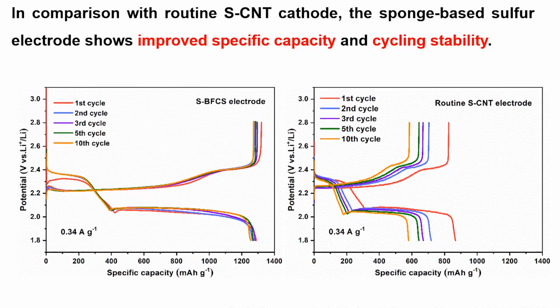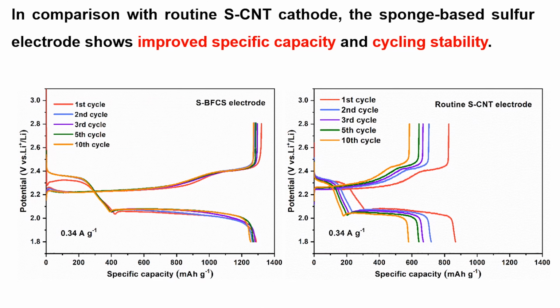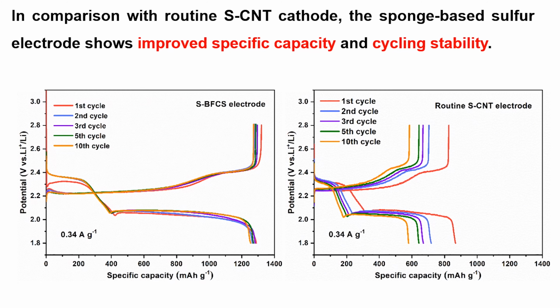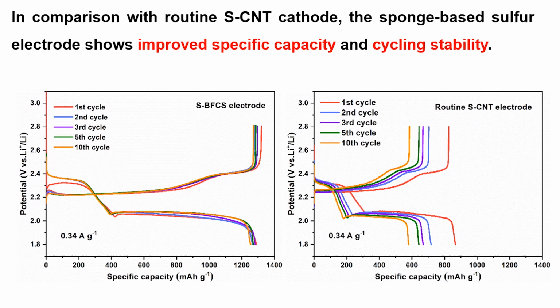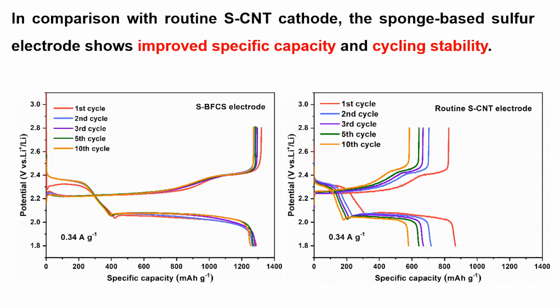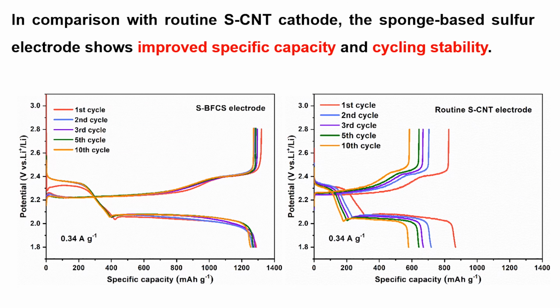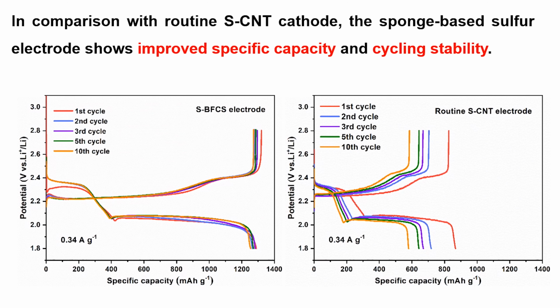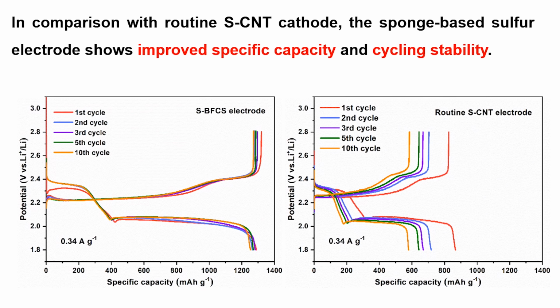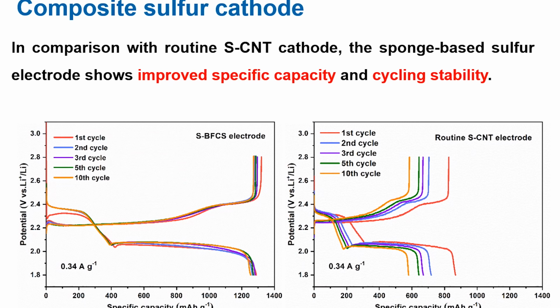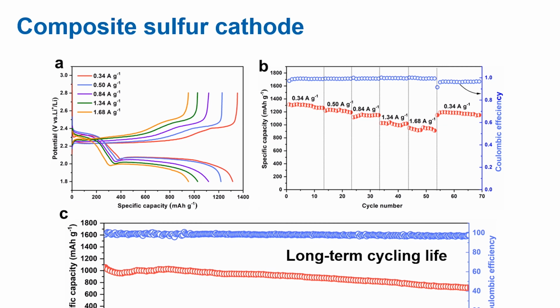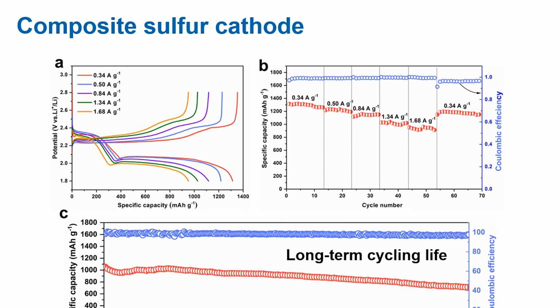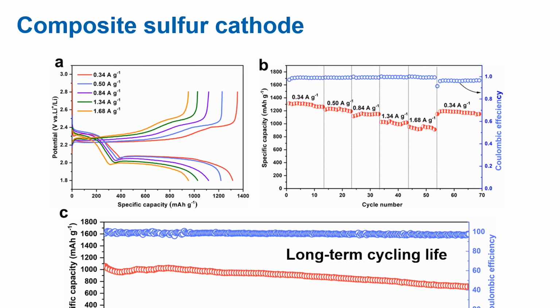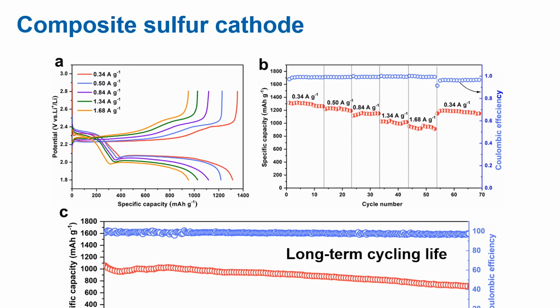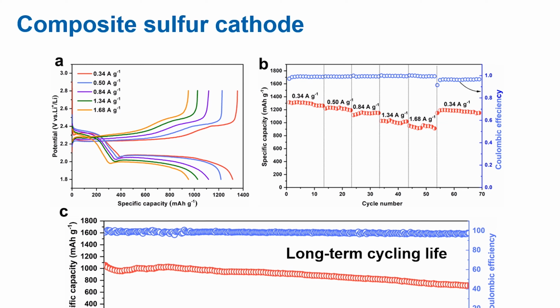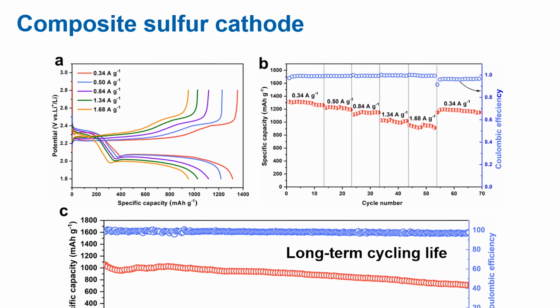From the charge-discharge curves, we can see that in comparison with the routine sulfur carbon nanotube cathode, the sponge-based sulfur cathode shows both improved specific capacity and cycling stability. It also shows good rate capability at high current densities and long-term stable cycle life over 300 cycles.